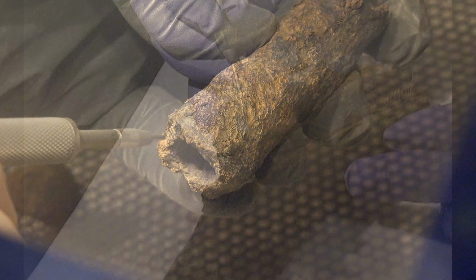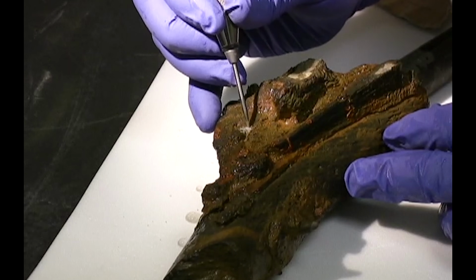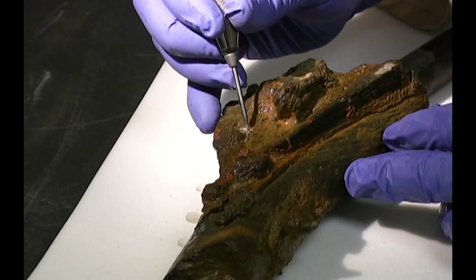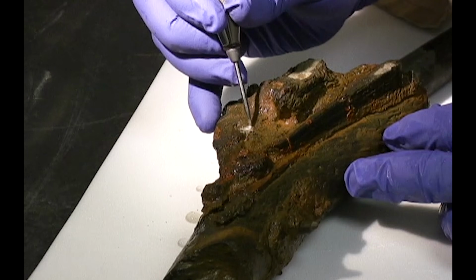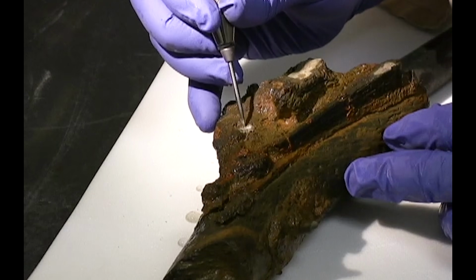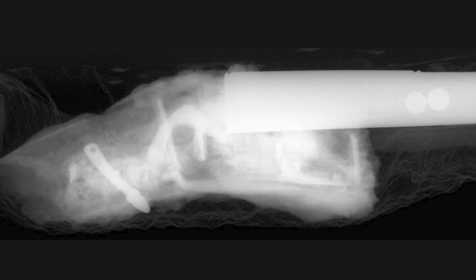So I went back to the air scribe, and we worked several hours on the lock plate to reveal the various components, the machinery, the working parts of the lock plate. But over time, we started to hear a little bit of rattling from within the barrel. Now, earlier x-rays showed that there were 2 lead shot in the barrel of the pistol, meaning it was double loaded. We knew that that was what we were hearing, those two lead shot rolling around.